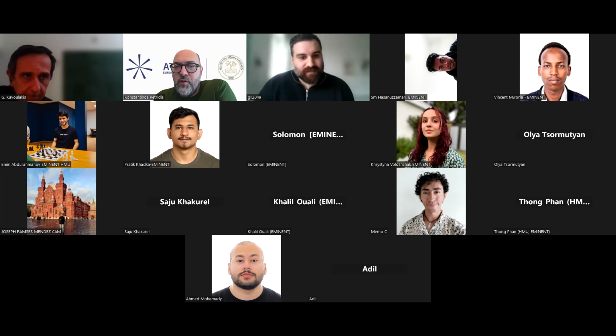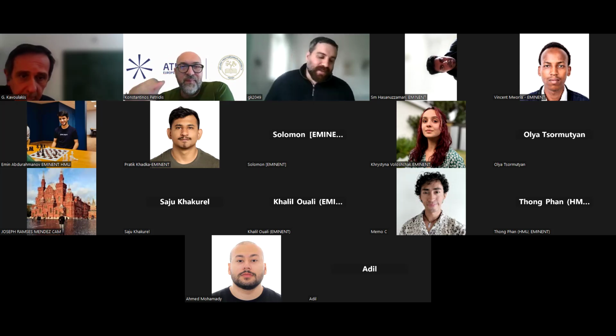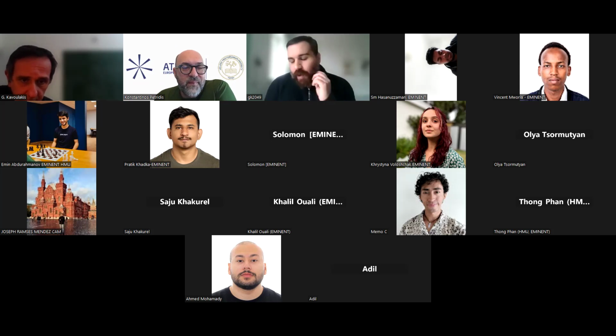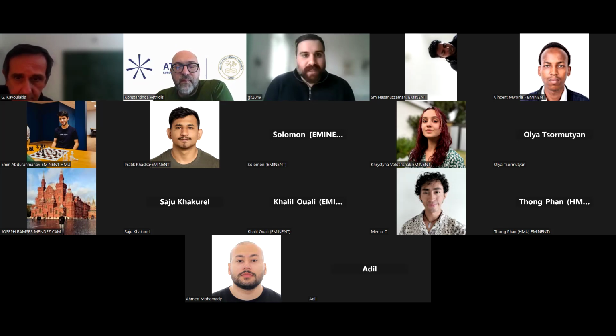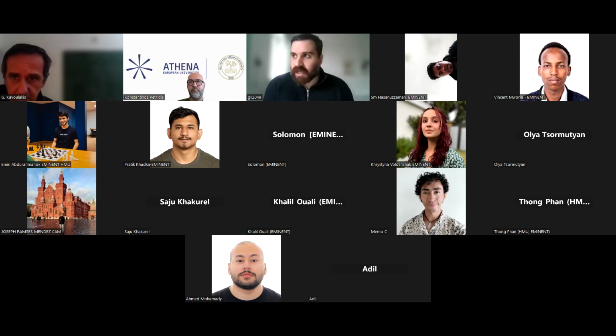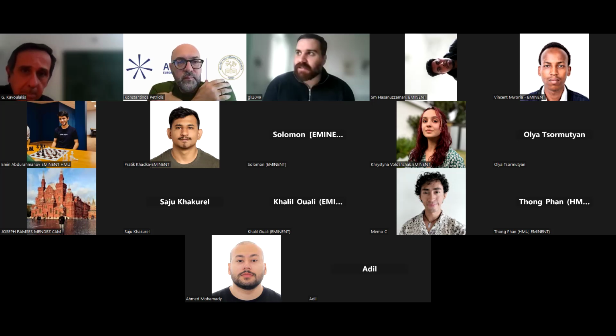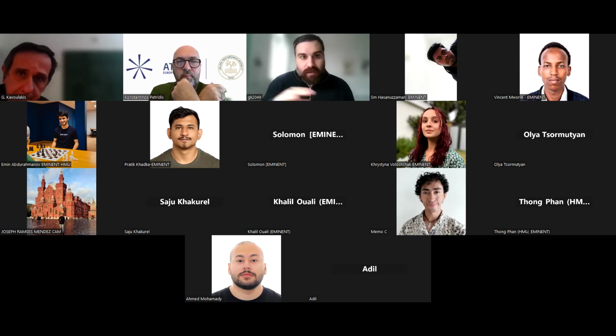There is another question. Sorry, George. Sure. From Khalil. What is AFM ironing? So yes, this is a technique that is widely used. When you do fabrication, not all the labs have the ability to have everything inside the glove box. Therefore, a lot of fabrication happens outside of a glove box in ambient conditions. And I mentioned that 2D materials are very susceptible to the external environment. So they will attract all the molecules from the atmosphere, all the adsorbents, and you have to get rid of them to actually create a uniform interface.